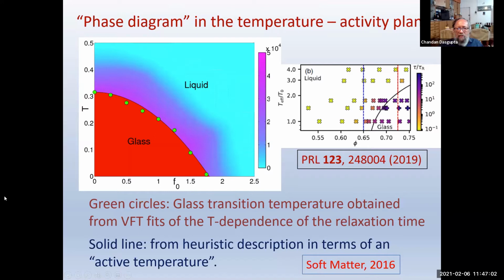I just want to remind you that the experiment that I told you about, Janus colloids, also sees a kind of phase diagram, where the phase boundary separates the glass phase, when there is no large-scale motion, from a liquid phase. Instead of looking at the temperature, they're looking at the density, the packing fraction. And this axis is a measure of the activity. So in the activity-density plane, again, one has a phase boundary which separates a glass from a liquid. Here we are not changing the density, but we are changing the temperature. And again, one gets something that looks like a phase boundary that separates these two phases.